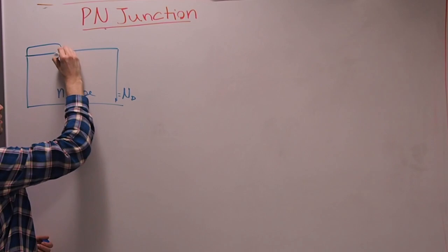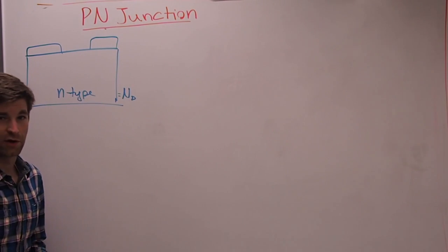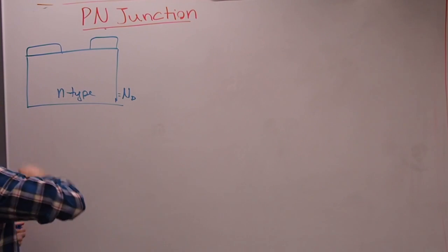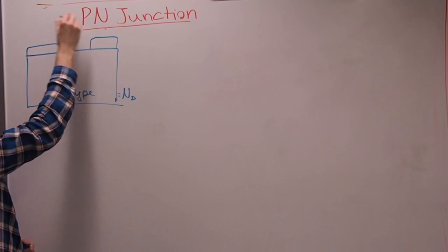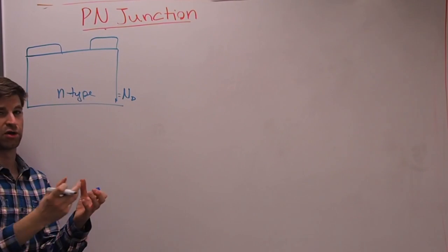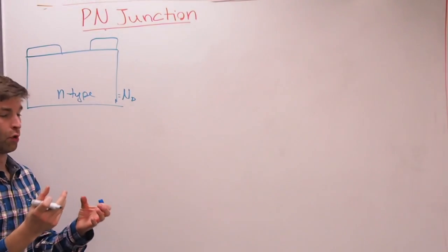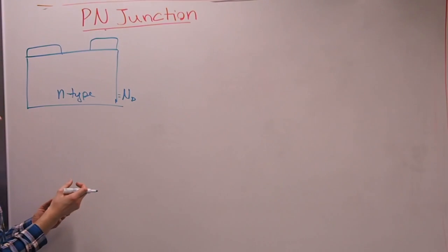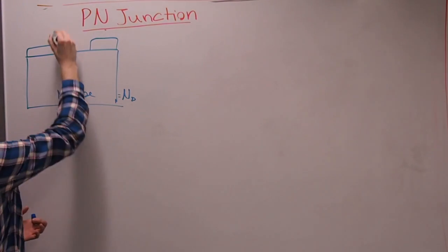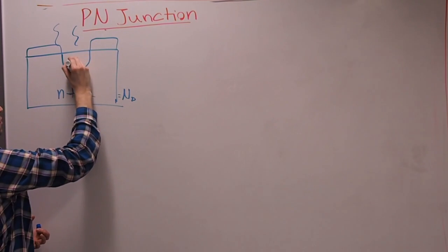So you would have this oxide like this. And oxide has very, very low diffusivity, right? It's very hard to diffuse anything into oxide compared to silicon. So then what they would do is they would use this carrier wafer that has a very high concentration of whatever acceptor atom you want to use. Maybe it was boron or something like that, which is a very common acceptor dopant atom. And we would diffuse, and we would create this well right here, which is p-type.